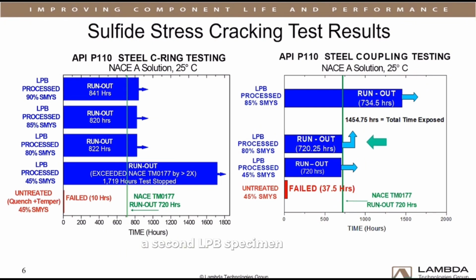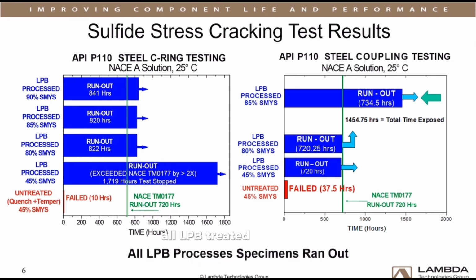A second LPB specimen lasted 720 hours at 80% SMYS. The pressure was then increased to 85% and the coupling ran for an additional 730 hours, after which the test was terminated without failing. All LPB treated specimens exceeded the typical hold time requirements at all loads in a sour service environment, proving that designed compression is effective in mitigating sulfide stress cracking.